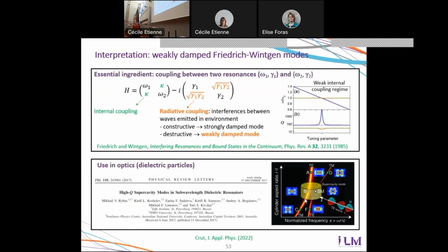It's actually a particular manifestation of what is called weakly damped Friedrich-Wintgen modes. So I will not describe this in detail, just tell you that there are two ingredients for creating such modes. You need to start with two resonances of close frequencies. So this can be two modes of the nanodisk whose frequencies vary differently with the geometry, that can become of close frequency accidentally. And then you need that these modes are damped by emission of waves in the same medium. It's the case in our experiments because emission occurs for all modes in the supporting substrate. And in this case, these waves can interfere.